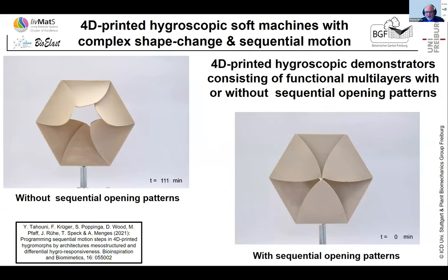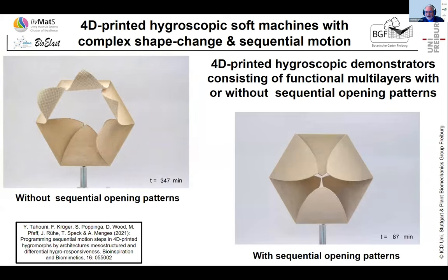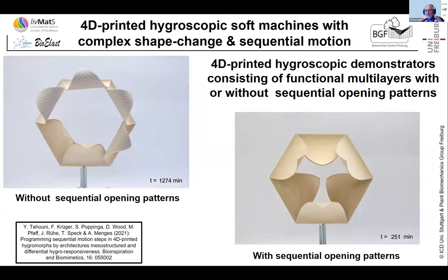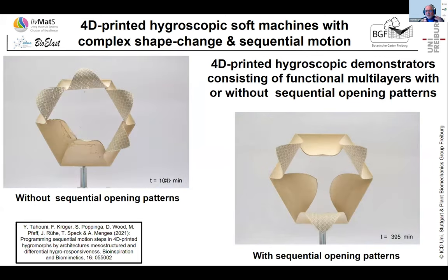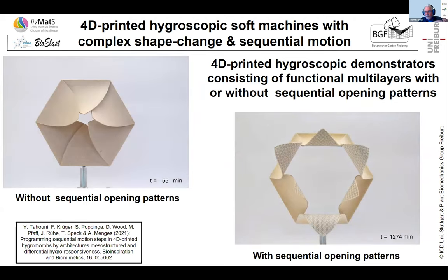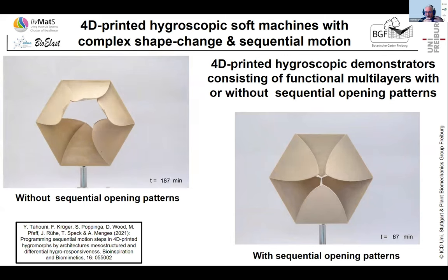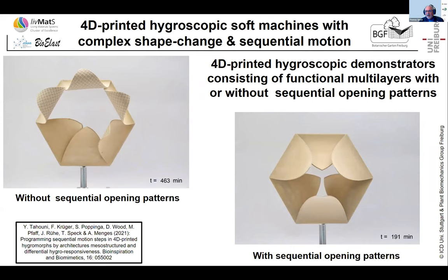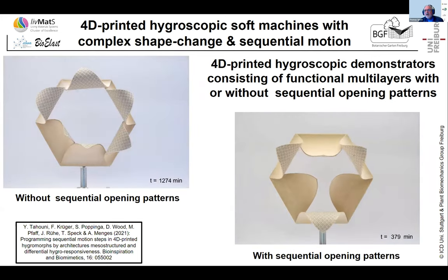And if you have a sequential opening, which you see down here, then you see that the outer three open first, and then the inner three open. So you have no interlocking, you have no interference. And this is orchestration we want to build, and which we have shown that it's possible in one material system by a clever arrangement of the different layers. And I think this opens a real wide field of application.